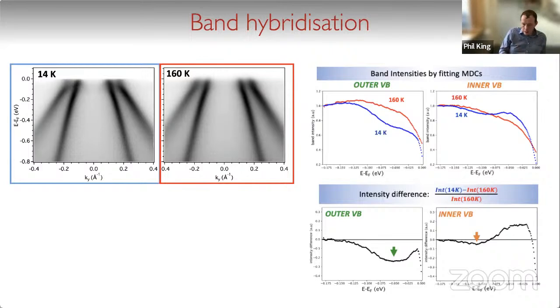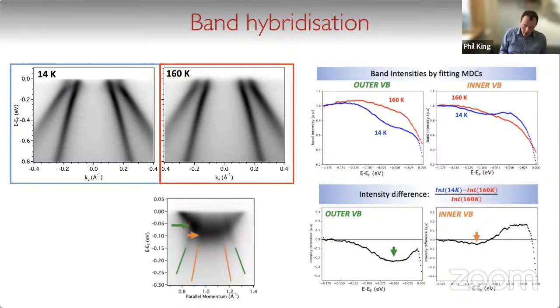And we can try and look at this a bit more quantitatively, and as I'm running out of time, I'll go a little quickly through this, but we can fit the MDCs, momentum distribution curves, to these spectra. And when we do that, we find clear evidence of band hybridization going on by these dips in the spectral intensity from the fitting. And if you look at a difference plot of these down here, you can see that exactly where the backfolded conduction and valence bands cross at these green and these orange arrows, you get a substantial suppression in the spectral weight pointing to band gap opening.